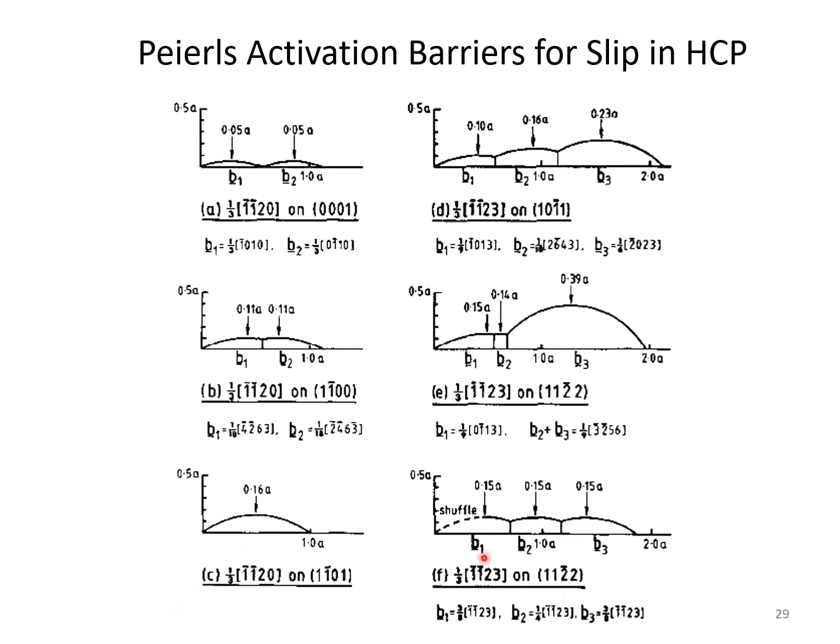And I think I demonstrated it for hexagonals there. I'm not sure if I did. I hope I did. But for the hexagonal close pack systems, I mentioned how the different slip systems have planes of different properties when it comes to slip. And it boils down to the atomic arrangement within the planes. They're not really planes exactly, in that they're not exactly flat. They can be corrugated, slightly ruffled, but the atoms can still glide with respect to one another.